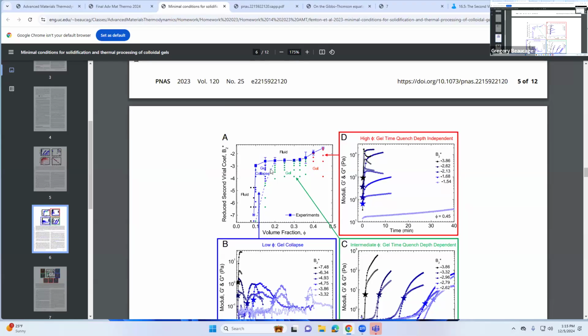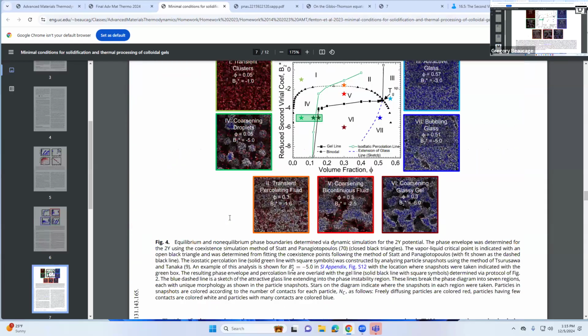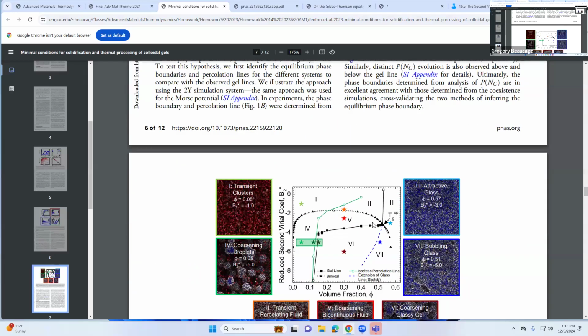Under the second option, phase separation, the thermodynamic model, there's a relationship between this gel point and the phase separation point that you can see in the second to last plot. There's a fixed distance. You phase separate, and at some point in the quench, this is a raising temperature quench because it phase separates when you heat it, you find a point where you get gelation. So the two things are linked. If you knew what that delta T was, you could predict the phase diagram from the gel point. Yes, I guess that's kind of what you could do.